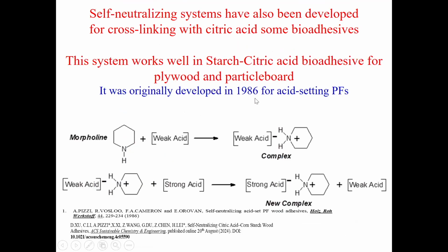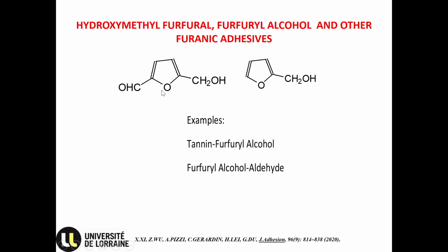It was developed in 1986 for acid-setting phenolic resin. You have the morpholine, that molecule there, which plus a weak acid forms a complex that is actually quite stable. Then when you put the complex in a glue and add the strong acid that cures the glue, in this case the citric acid, the complex reforms with the strong acid, not with the weak acid. That means only the weak acid remains, and consequently the pH in the glue line is much higher. So there are not very many problems in using this.